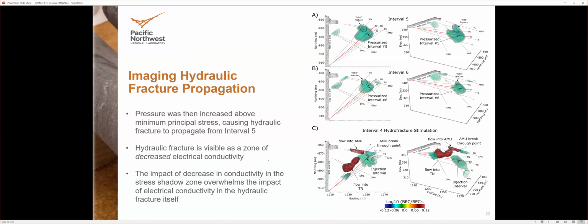Yes. Okay, good. So the fracture propagated from this isolated interval through here, and we don't actually see the hydrofracture in terms of the increase in conductivity; it's probably a very small hairline fracture. And as Jeff mentioned, what we actually see is the stress that fracture causes, and that's this decrease in conductivity here, and also along this borehole. And here's just an oblique view of that, where we're injecting here, the fracture runs through this region, and we're seeing the shadow stress caused by the fracture rather than the fracture itself in that case.